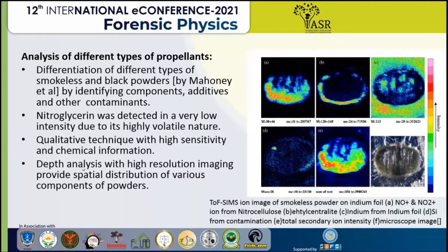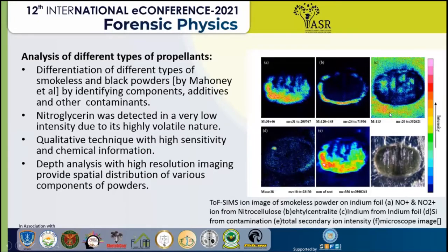In the imaging of propellants, the components of the powder are visible. The smokeless powder was pressed against an indium foil and examined; the spatial distribution of indium foil can be seen, along with ethyl centralite — a coating for smokeless powders — present only around the corners. Silica contamination of unknown origin was also identified. This can also be used to individualize one type of powder from another.